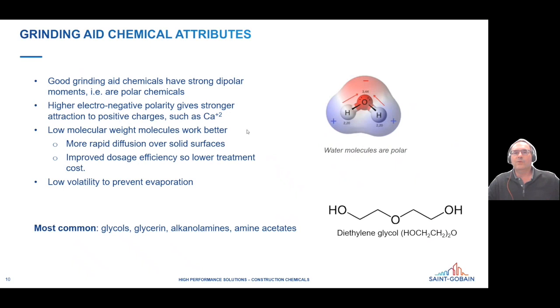So what are some of the attributes of a good grinding aid chemical? Well, they tend to have strong dipolar moments. This really helps them adsorb quickly onto the surface of the cement particles as they're being ground. So you need to have a strong attraction to the positive charges on the particles, such as the calciums. Low molecular weights tend to be a little bit more nimble. They can quickly diffuse over and do the job before the particles have a chance to reagglomerate. And you do need low volatility chemicals as well. So the cement grinding mill is quite hot. It could be up to 150 degrees C.